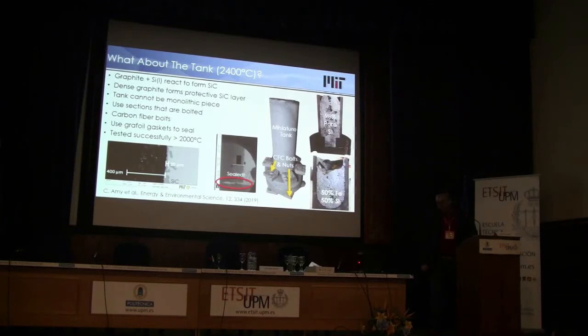And so we were interested in trying to prove or see if it was possible to actually make a tank out of multiple sections of graphite that are bolted together with a seal. The key is a seal. Right at the interface between two pieces that you just mechanically butted up against each other is where the liquid will want to leak out. It's well known, if you put silicon in contact with graphite, they're going to react, you form silicon carbide.